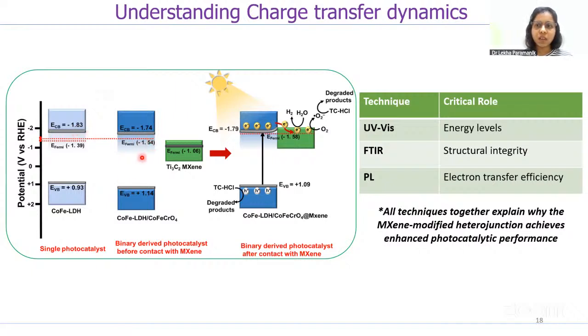Then after the heterostructure formation, it has the conduction band of minus 1.74, and by using the UPS analysis, I found that the titanium carbide MXene has a Fermi level of minus 1.0. As it's a metallic character, it has a very high work function with low Fermi energy level. As a result, the electrons would migrate from the conduction band to the titanium carbide MXene surface, and the electrons will be abundantly available for the photocatalytic application.